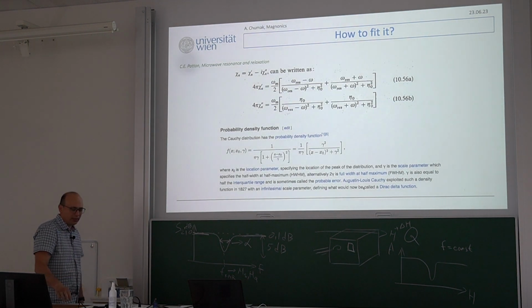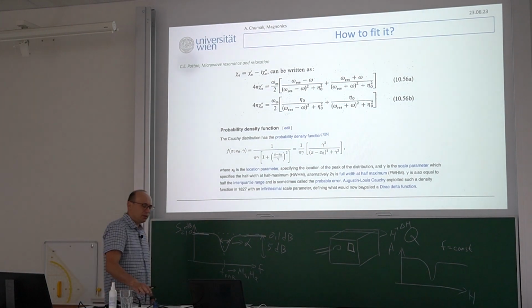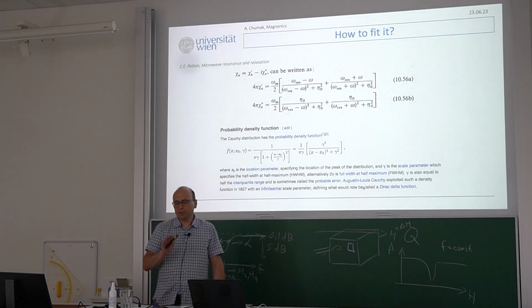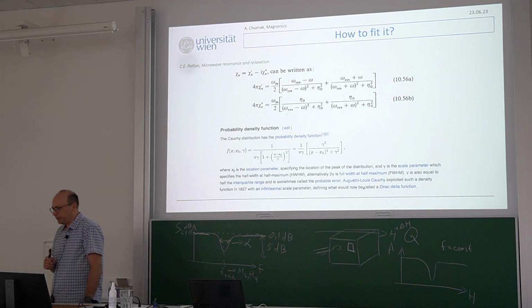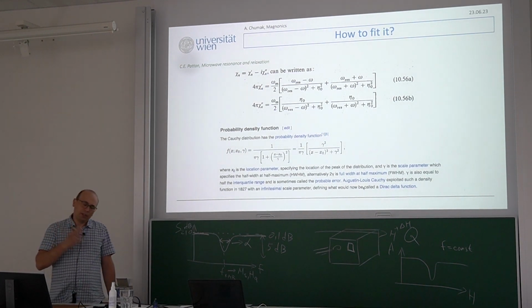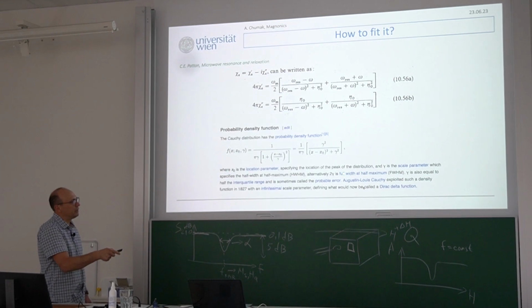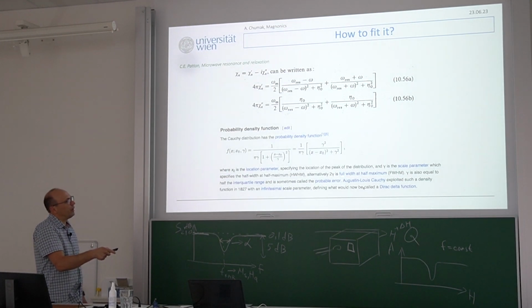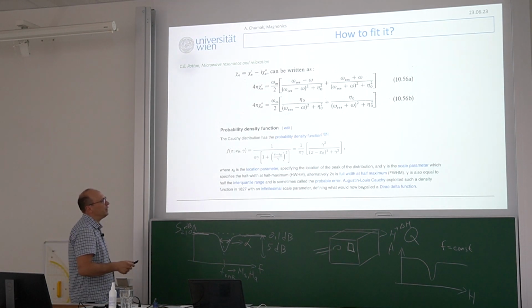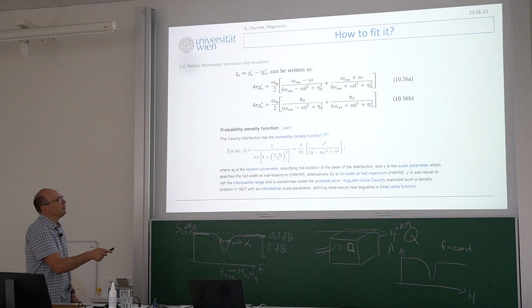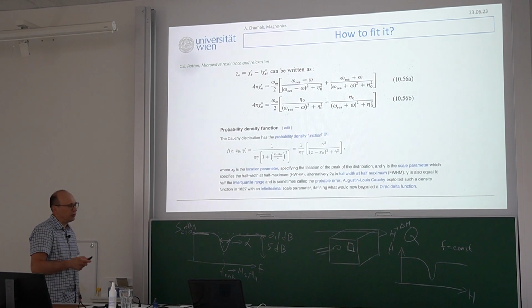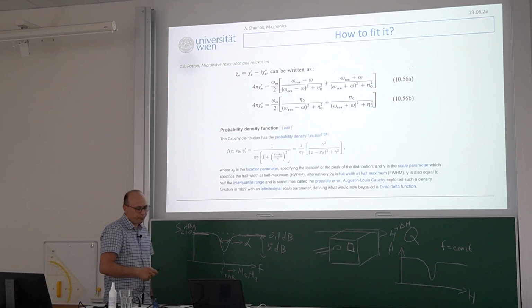When we discussed damping, I especially devoted one slide or so to different types of damping: omega 2 prime, the imaginary part of frequency, lifetime, full width half maximum, and half width half maximum. So be careful what is measured, because it's very easy to lose a factor of two here. Therefore, check what your gamma is.